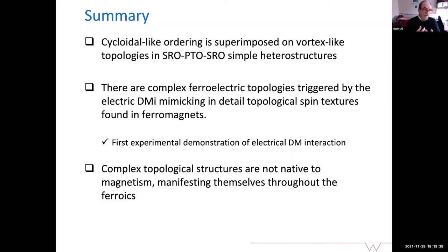But the beauty of this is that, unlike the magnetization, where you can determine the arrangement in reciprocal space only with neutron diffraction, in this case we can do that with X-rays. It's much simpler. We can do it in the lab. And then we can get exactly how it is distorted, if it is a periodic distortion, by X-ray. So we have two different tools: the reciprocal space with X-ray, which tells us the double Q structure, and the real space, which we can map by transmission electron microscopy. So it's something magnetism does not have.